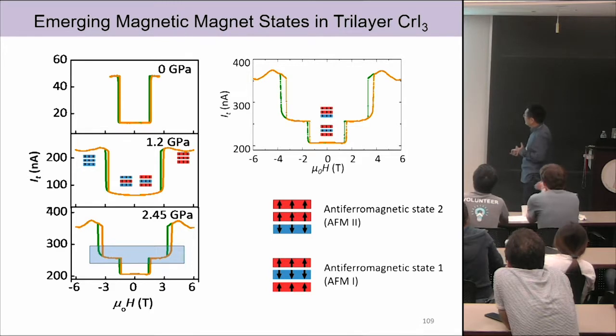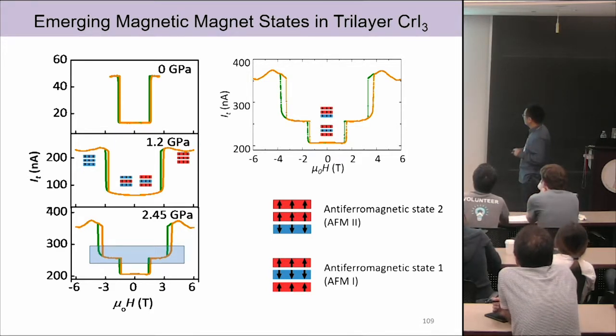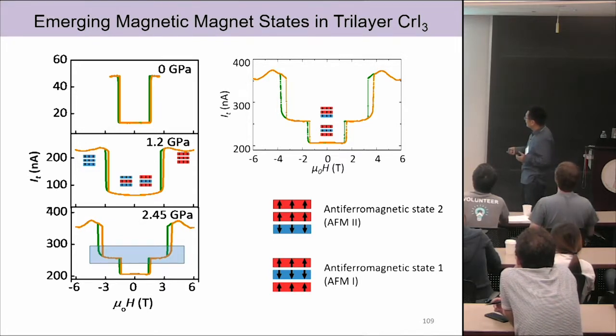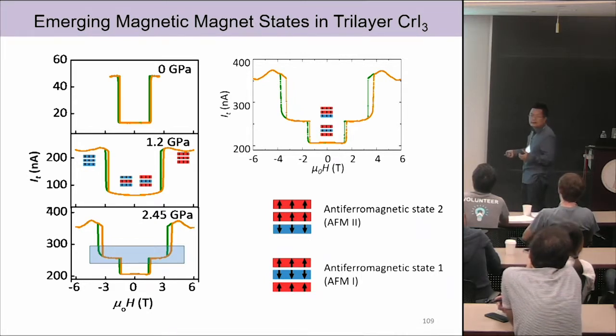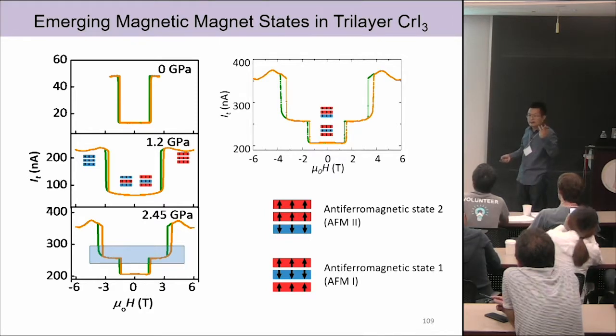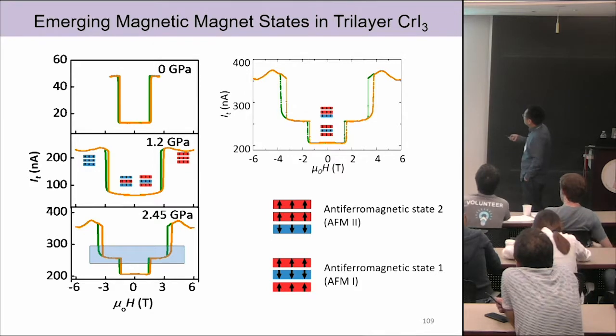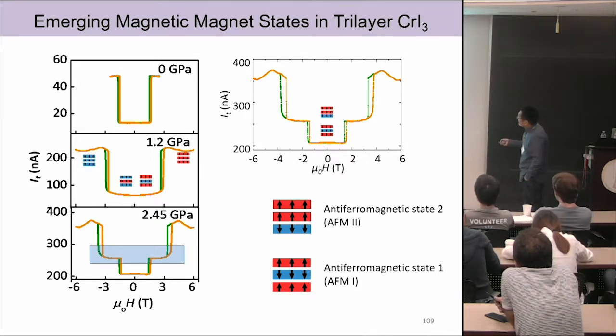So here, I define two types of antiferromagnetic states. The first one is called antiferromagnetic state 1, or AF1. AF1 is just the one I already talked to you about, with two antiferromagnetic interfaces. Spin up, spin down, spin up. So there are two interfaces, and it's antiferromagnetic, just like natural crystals. But for antiferromagnetic state 2, or AF2, now there's only one antiferromagnetic interface. The other interface becomes ferromagnetic.